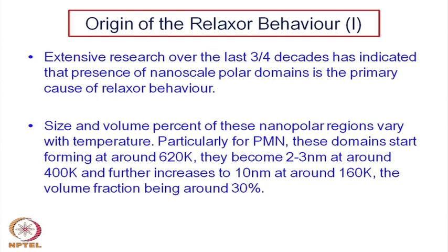Here it is nanoscale domains, very fine nanoscale domains, and they are not a fully ordered structure or a fully crystallized structure. They may be crystallized, but so far as the domains are concerned, they have a disordered structure. Now, because of this disorderedness, instead of a single relaxation time, as in the case of barium titanate, you have a spread or a distribution of relaxation times.